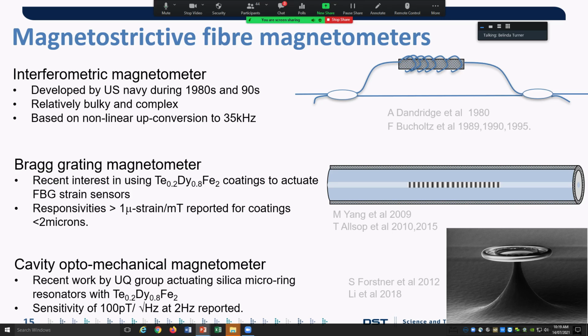So there was some work about 10 years ago where people were coating Bragg grating sensors with magnetostrictive materials, and they showed they could get a strain of about 1 microstrain per millitesla. Well, that was what was reported in the literature.